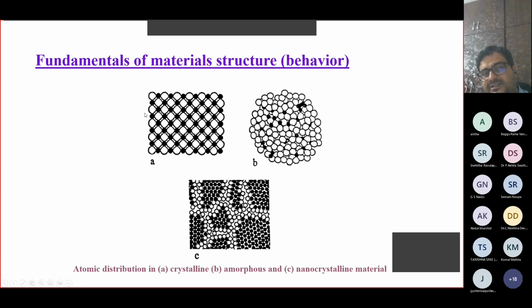So therefore, the lattice defects that I mentioned, the vacancies, interstitials, impurities, dislocations, grain boundaries, stacking faults, inclusions, and impurities, all those things are of some meaning only in case of crystalline material, not for amorphous material.